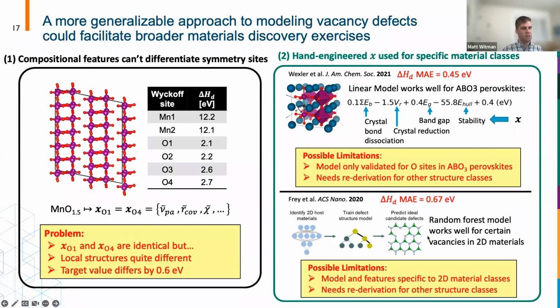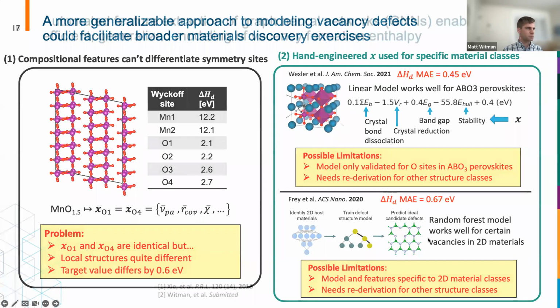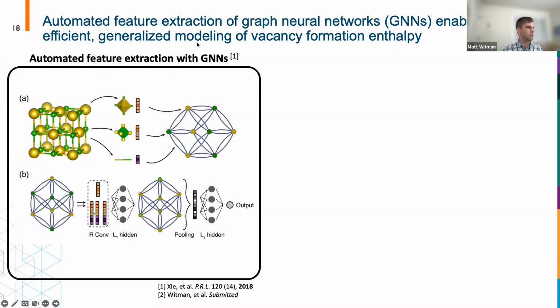Kind of a similar thing was using random forests to predict vacancies in 2D materials. But again, there's similar potential limitations where it's validated for these 2D material classes, and you would need to rederive your model as soon as you went to a different structural class. So one thing that's really attractive is the automated feature extraction capabilities of graph neural networks. And you can use this for efficient and generalized modeling of vacancy formation enthalpy.